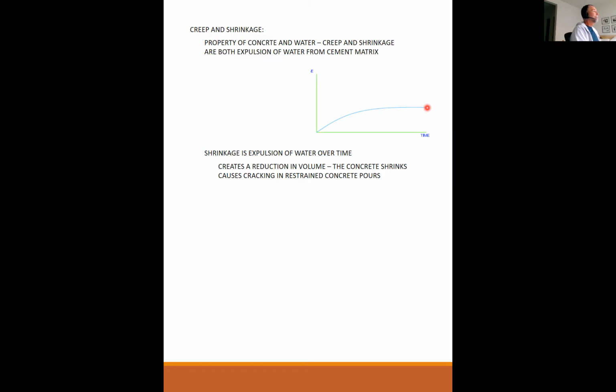So think of it like a slab on grade. Think of pouring a patio or pouring the concrete in your garage. When you pour that concrete, you pour it up to the forms to a certain size. We do everything we can to slow the shrinkage down. We cover it with plastic, or we soak it in water. We do whatever we can to slow down the shrinkage. But inevitably, water is going to come out of that concrete into the atmosphere, and that slab is going to shrink. Now, that slab is not free to just shrink as much as it wants. There's friction between it and the ground, or it may be tied into walls, or it may be in some way restrained. And that's where you get cracking in your floor slab.